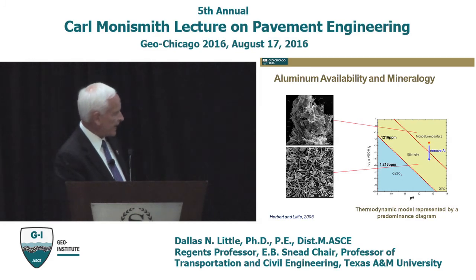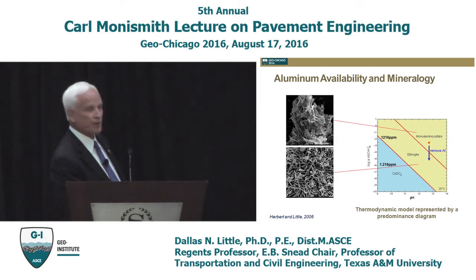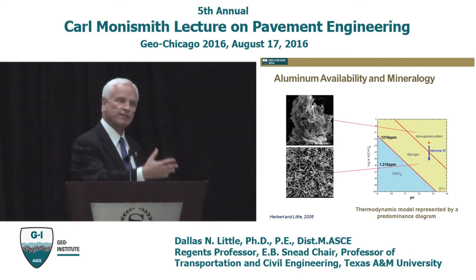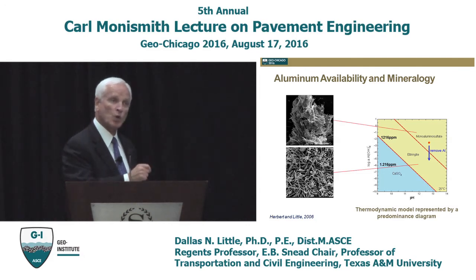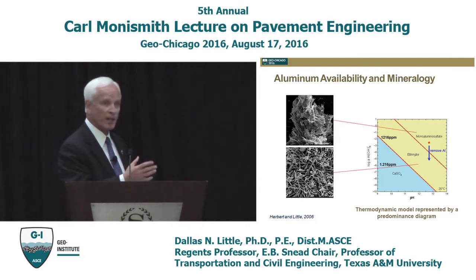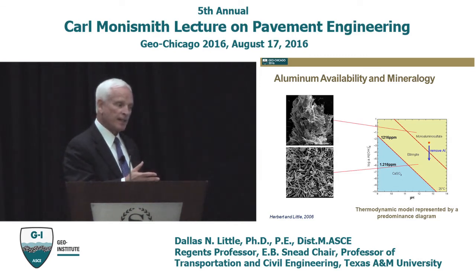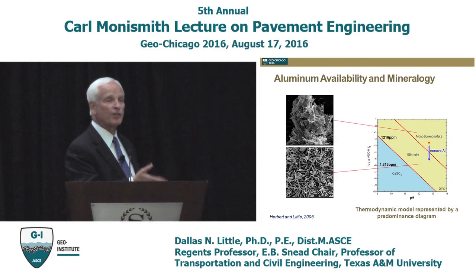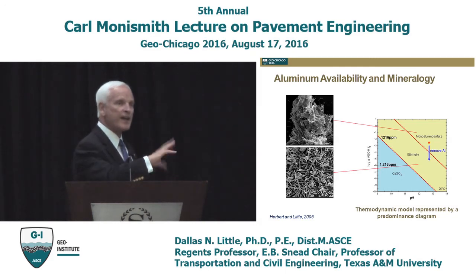Here's something that we did in the lab that's quite interesting. Here we were just trying to test the power of the thermodynamic stability diagram. In this particular case, monosulfoaluminate is a calcium sulfate aluminate compound that's high in alumina. And ettringite is the trisulfate form, where the sulfate ratio is high compared to the alumina ratio.